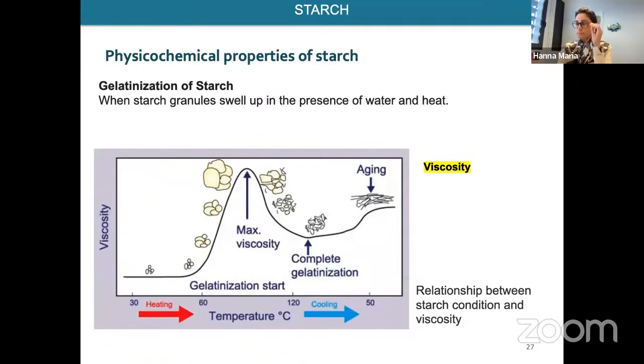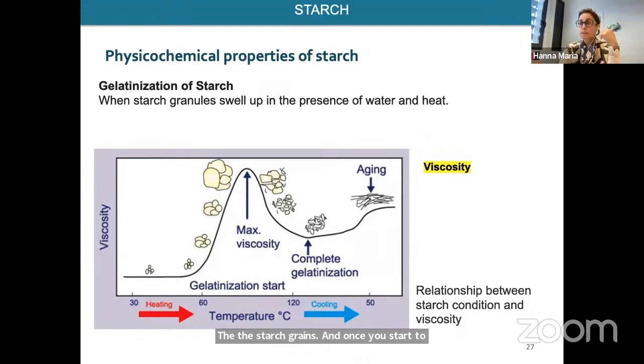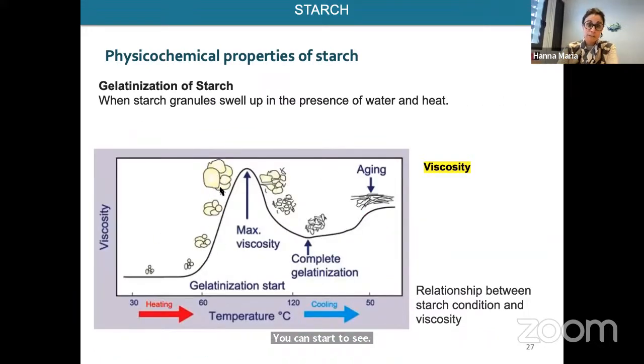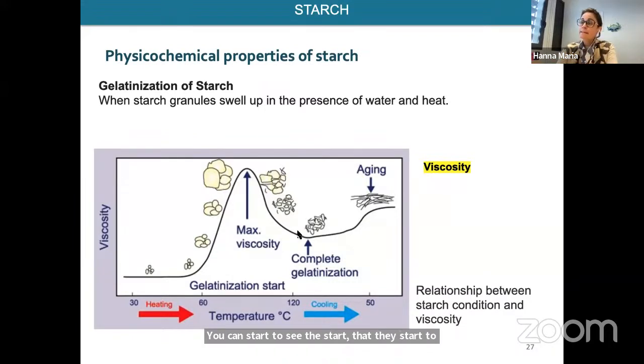So regarding the viscosity, how does the viscosity evolve during the gelatinization of starch? Here again, around 30 degrees you have the starch grains, and once you start to increase to 60, 80 degrees, you can start to see the starch granules swell. And then around 90 or 100 degrees Celsius you have the maximum viscosity of your starch solution, as you can see here.